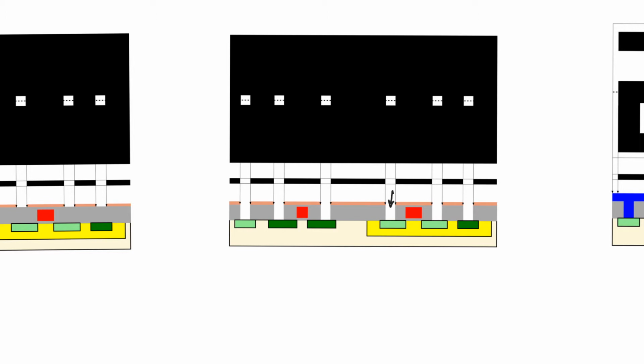This step is kind of challenging because we have to time it right. We have to bathe the wafer long enough so that we have opened all the way through down to the N plus and P plus areas. On the other hand, remember that wet etching is also going to eat laterally, so the drawing that we are using here is ideal, and the real situation is going to also open up laterally. The longer we expose the wafer to the etchant, the more lateral etching there will be. So the deeper the contact, the harder it is to make.